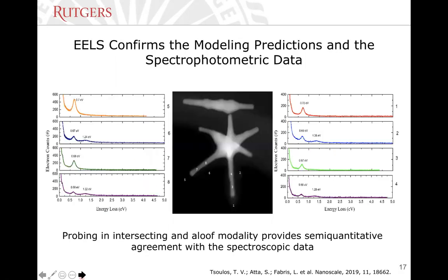We did one extra step. We decided to go and look at the single particle from the single particle standpoint. We decided to go and look for these modes, for the first, second, and third harmonic modes. And we did that using electron energy loss spectroscopy. We know very well that we cannot exactly compare photon-based excitation with electron-based excitation. There is a momentum difference here. We need to take this into account, but semi-quantitatively, we can find that there is a nice match between the results. And that was really exciting for us.